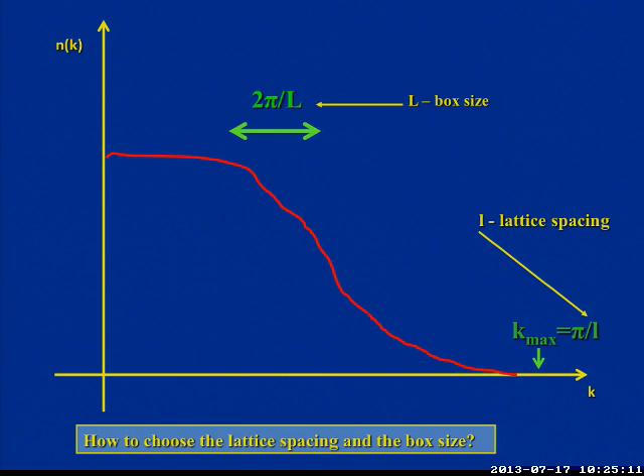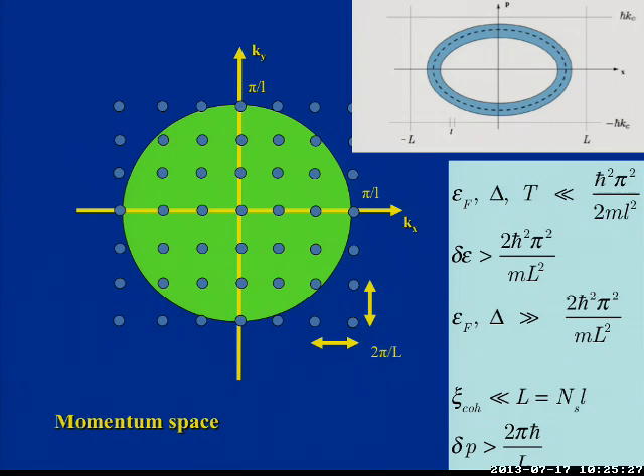If I want to go up to this momentum, this is given by the inverse lattice constant. So if I'm interested in whatever properties here, I have to choose carefully the size of the box and lattice constant in order to reproduce those properties. Okay, so this is how we set the problem. Now, you can think of this in phase space. So if you do classical phase space, this is coordinate and this is momentum. This is the size of the system. It goes from minus L to L. In momentum, since we have fermions, we occupy states with significant probability from minus k to k. So you want to occupy this thing. Once you fix this, you fix the lattice constant. And this fixes the size of the box. Okay, so this is how we operate.